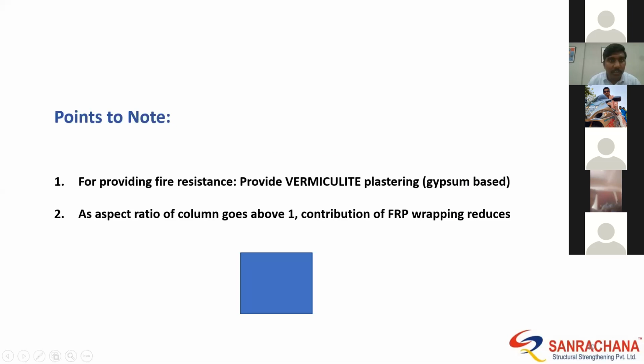much compressive strength capacity. So in addition to all that, you can provide vermiculite plastering, which is a gypsum based plaster, on top of FRP for improving its fire resisting performance, wherein commercially, as per law, it is required to provide a certain fire rating, as in the structure should retain its strength for a given amount of time, like 1 hour, 2 hours or 4 hours, based on the type of building, for which we can design how much thickness of this plastering is required.